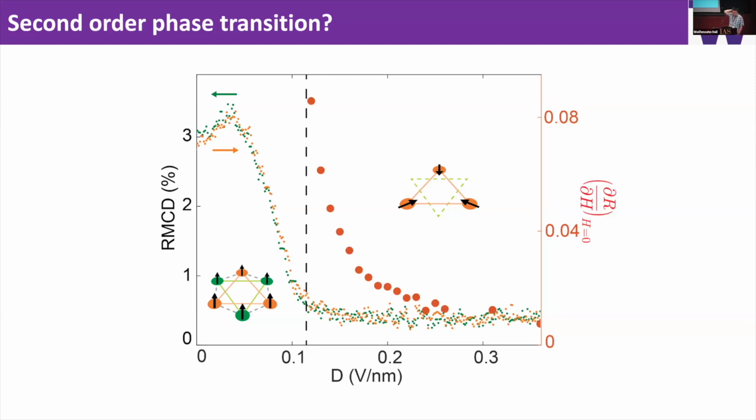The other thing we did is measure this slope, as I talked about in previous slides, at different electric fields. Then I plot the slope as a function of electric field. You will see that the slope of the magnetic susceptibility basically reaches singularities near the phase transition boundaries. So this also gives a signature that the phase transition could be continuous in such a system.